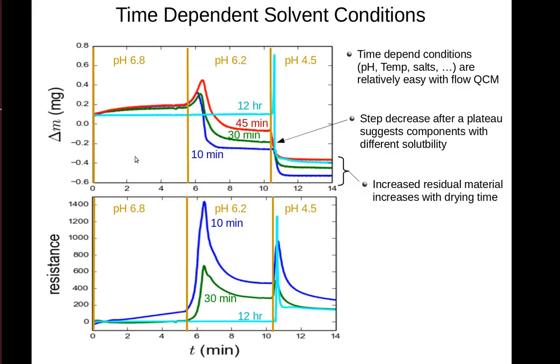QCM also affords us the ability to change the dissolution conditions while the experiment is being run, slightly easier than a traditional dissolution measurement. Here we have mass versus time. This time we're going to have step changes in the pH: 5 minutes at a pH of 6.8, then another approximately 5 minutes at a pH of 6.2, followed by a step change to a pH of 4.5. And this is done for polymer films dried at 10 minutes, 30 minutes, 45 minutes, and 12 hours.